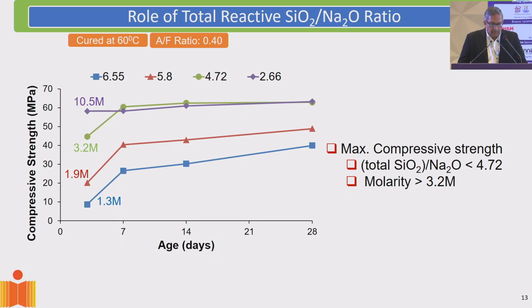If you do that, what we found is that the reactive silica to sodium ratio, and these lines that you see are for different reactive silica to sodium ratios, varies from 6.55 to 2.66. The 2.66 is on the top, the 6.55 is the line at the bottom. The geopolymerization was performed using sodium hydroxide solutions of different molarity. What you find is if you increase the molarity beyond 3 molar of sodium hydroxide, it really doesn't make any significant improvement. So you really don't need a very high molarity solution like what people have used in the literature. You don't need 14 or 15 molar sodium hydroxide. You can manage with 3 molar.